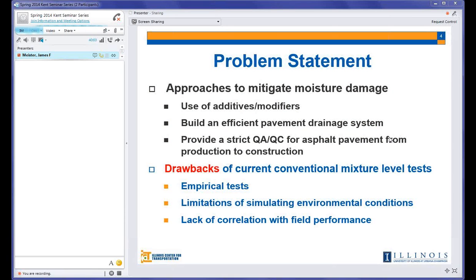Another challenge for moisture damage is how are we going to evaluate the moisture susceptibility of asphalt mixtures in the lab? There are a lot of laboratory tests in which we can indicate whether this mixture is moisture susceptible or not. But most of the time, those mixture level tests share some drawbacks, which is first, they are empirical tests. They are not, unfortunately, built on fundamental properties of the asphalt mixture. So you can guess that the results will keep changing. There are limitations on the simulation of the pavement climatic condition that the pavement suffers in the field. And that's also a major drawback.